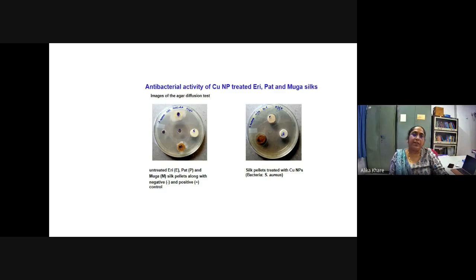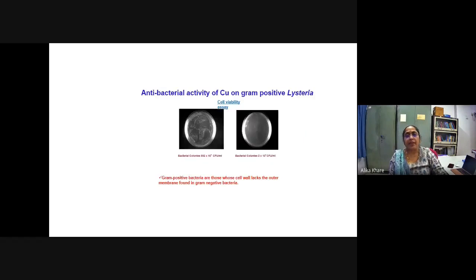When it was not treated with the nanoparticle, one can see good growth of the bacteria. But when it was treated, one can see the inhibition around this palette. So this shows that the antibacterial properties are getting enhanced, and it can be used to protect the wound or wherever we want better antibacterial property.